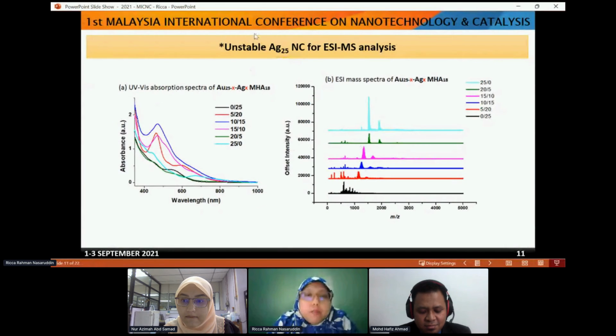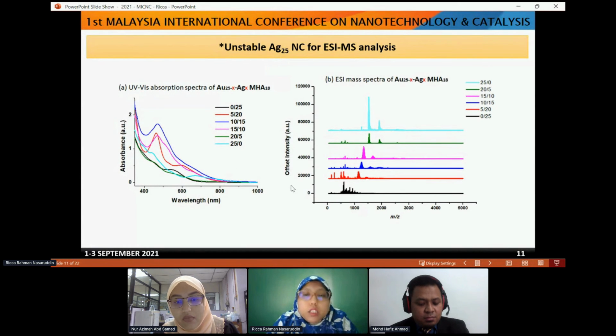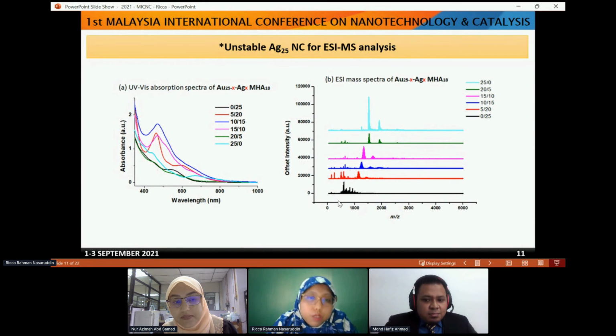So these are examples of what I mentioned just now. If I increase the ratio and try to produce silver 25 nanocluster using MHA as the ligand under that particular reaction condition, I can still obtain the cluster, but it is very difficult to identify using ESI mass spectra. Why? Because when you add more silver to the cluster, it is unstable under ESI mass analysis.